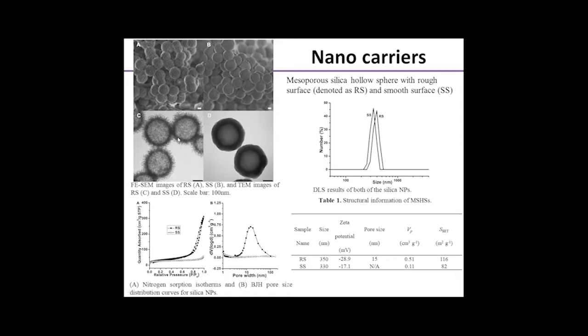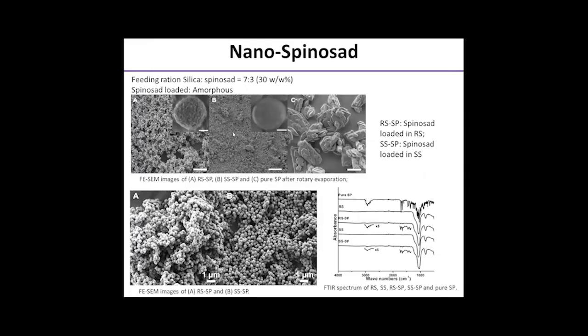between the surface spikes. A control material is also selected and prepared with exactly the same structure, except the surface is smooth. A rotary evaporation method was used to load the spinosad into the nanocarriers with a silica to spinosad feeding ratio of 7:3. The products are denoted as RSSP and SSSP, but here I will simply call them rough and smooth nanospinosad